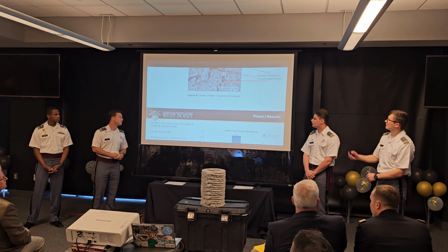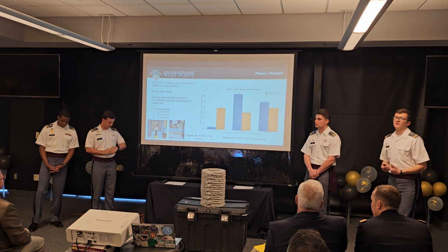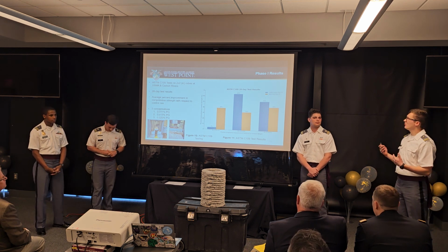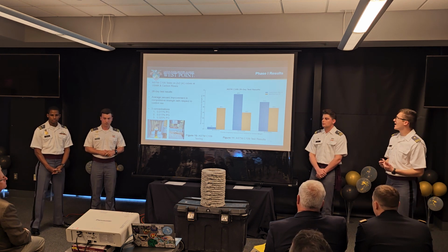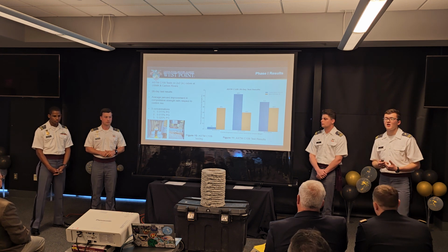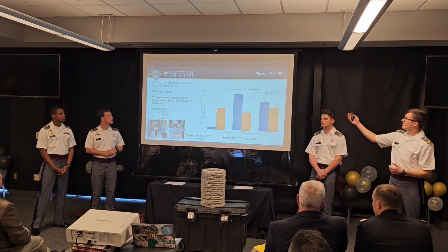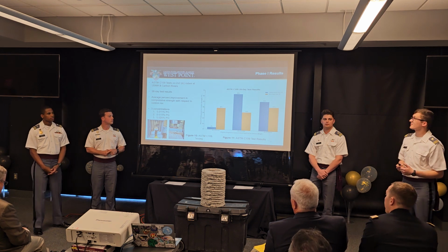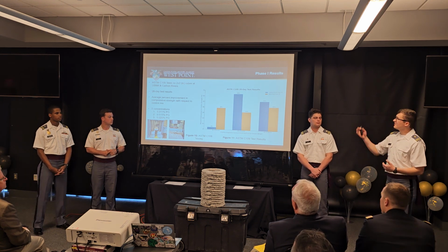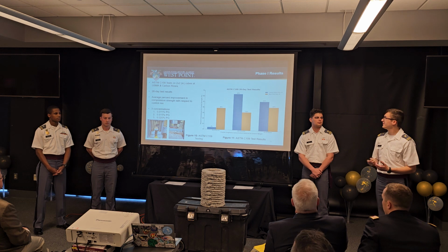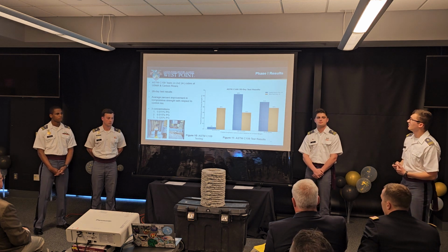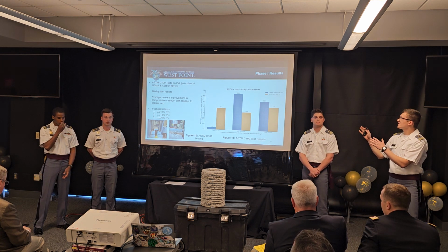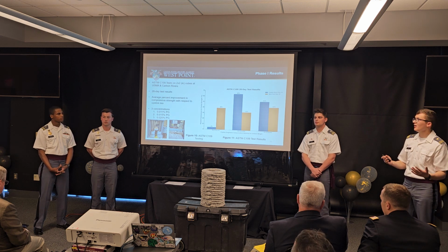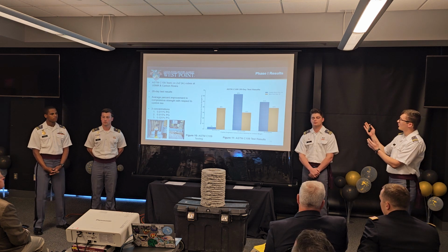Thanks, Nick. Just to go back to the concept of operations for phase one, as we mentioned, we conducted the ASTM C109 test, which is a standard compressive strength test for the concrete cubes, which we use 2x2 cubes to keep it at a small scale for efficiency. We tested these cubes for a 28-day period, and we got the results on the figure on the slide. What is important is that these tests were done both by the Cadet team at West Point, as well as our technical partner, Carbon Rivers.